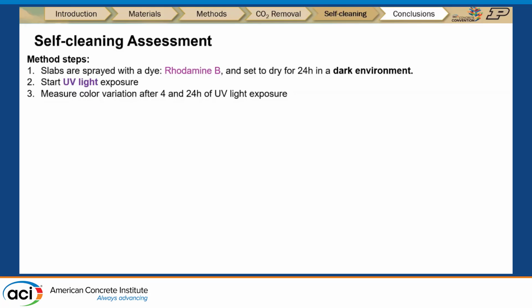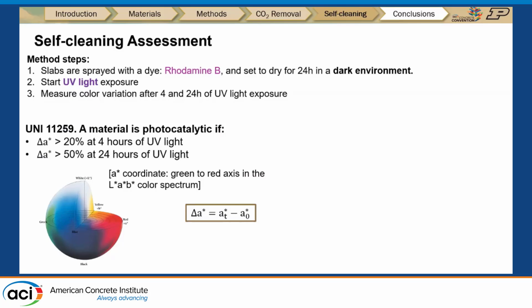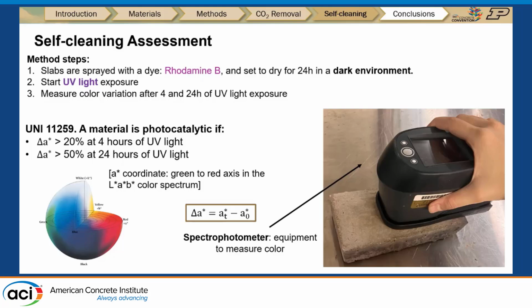After that, we start the UV light exposure, and we measure the color variation after 4 hours and 24 hours of UV light exposure. The UNI standard requires us to measure the color variation in the LAB color spectrum. The a coordinate is the green to red axis, and a material is considered photocatalytic if the change in the a coordinate is over 20% after 4 hours and over 50% after 24 hours of UV light exposure. A spectrophotometer measures the colors in the LAB system and is used for measuring the variations.